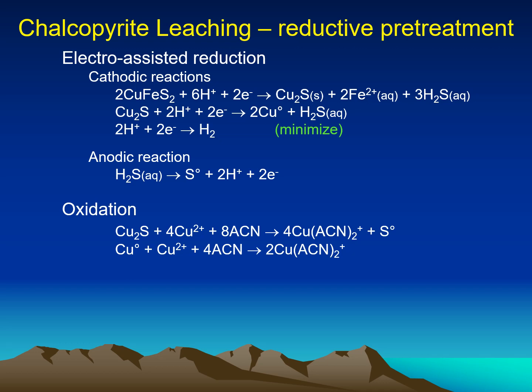The solid is then passed to an oxidation stage where the chalcocite and the copper metal are leached or oxidized with cupric ion in the presence of acetonitrile. The presence of acetonitrile allows the copper to be reduced from copper 2 to copper 1, to cuprous ion, and we have the formation of sulfur and the soluble acetonitrile complex with the cuprous ion.